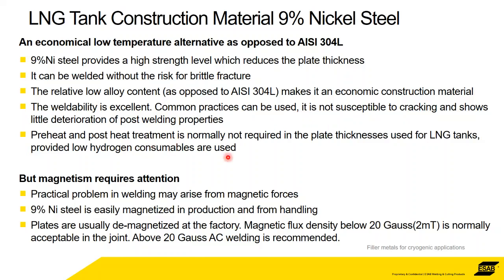Preheat and post-heat treatment are not normally required at these kinds of plate thicknesses, provided low hydrogen consumables are used. One thing to watch out for that's not common, so for someone operating in this kind of environment for the first time, this needs to be taken into consideration: magnetism, it can be a problem. Handling and moving these plates around, you've a great risk of increasing the magnetism within the base material. If it's not possible to demagnetize, if there's a magnetic flux density in the steel, then that can cause all kinds of problems when welding, specifically arc blow. The arc goes where it wants. So what we would recommend is a flux density below 20 Gauss. If it's above that and it's not able to be demagnetized, then AC welding would be recommended.